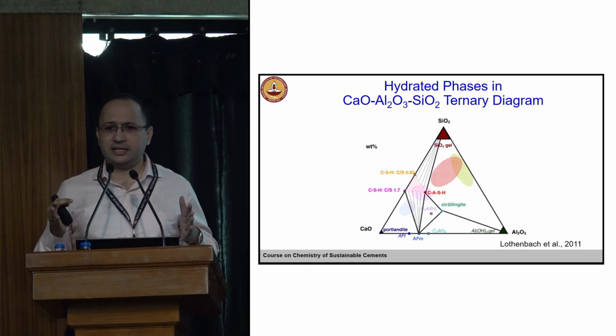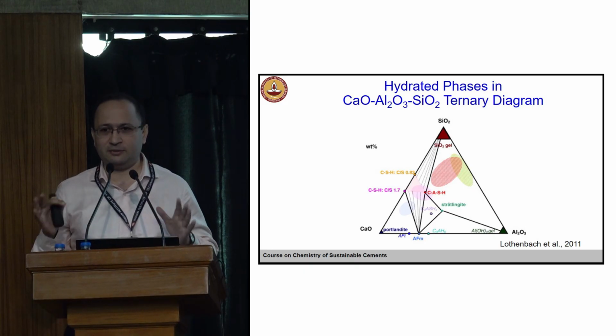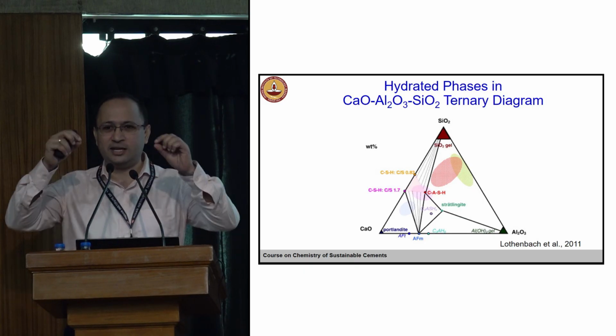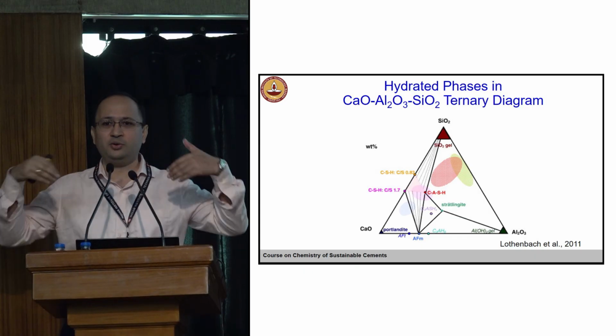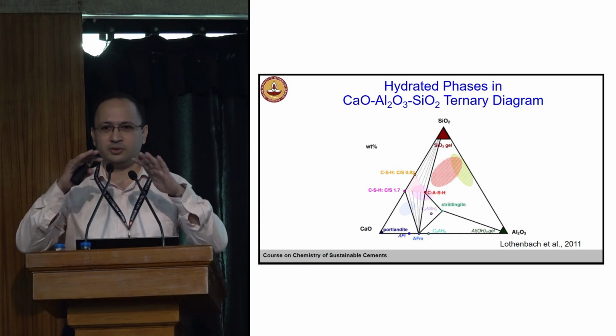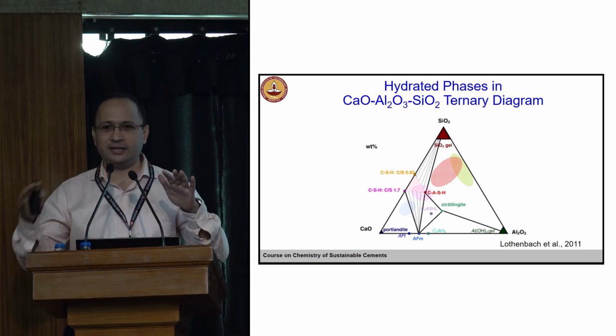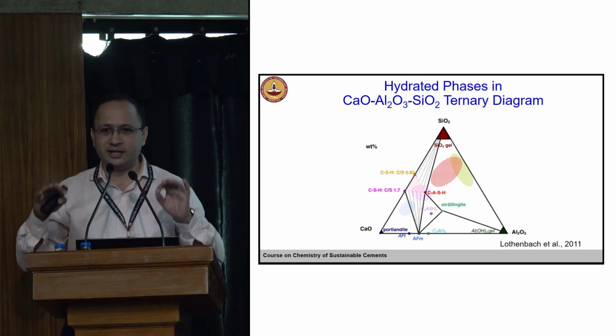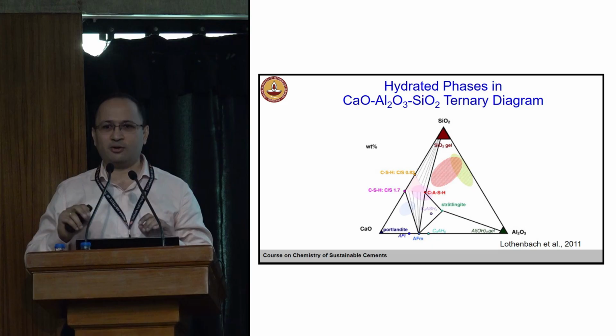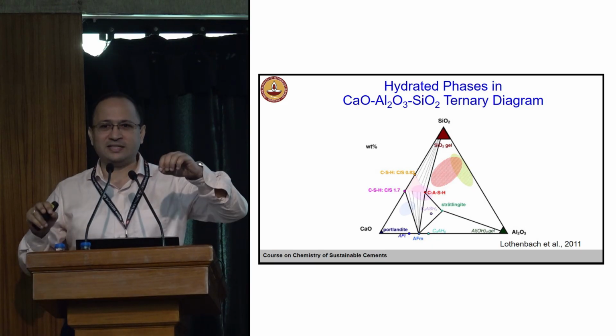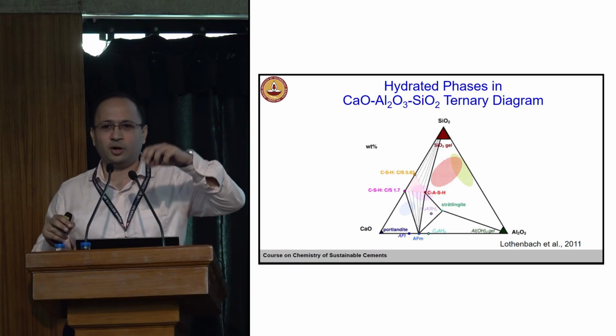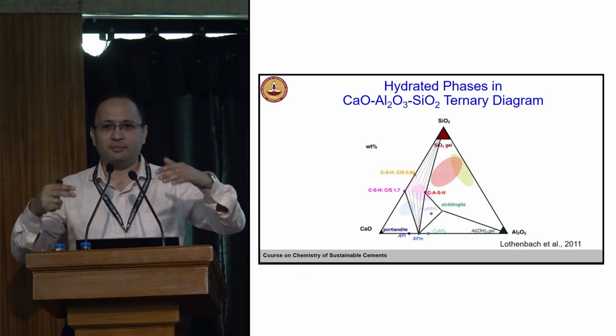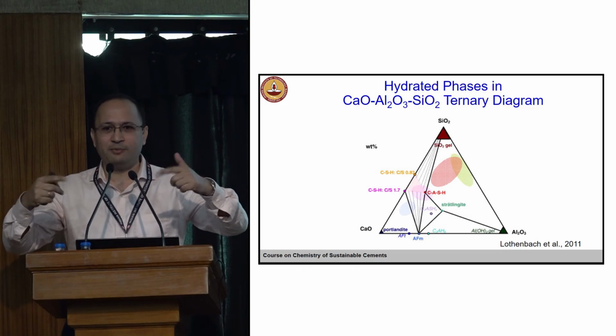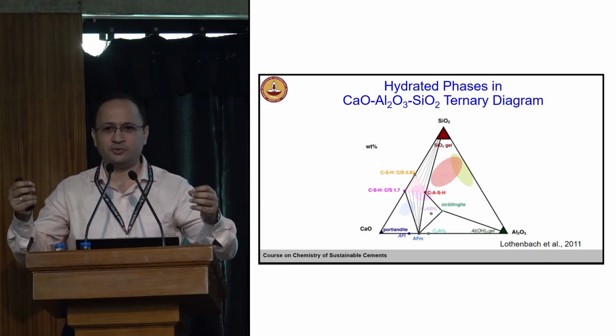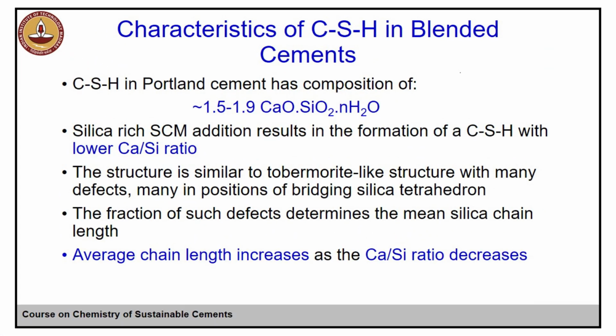Essentially, cement hydration is a dissolution precipitation reaction. If you have to understand cement hydration, things are dissolving, and then new things, reaction products, are precipitating. Dissolution is governed by undersaturation. Precipitation is governed by supersaturation, right? A simple example is, if you start adding salt to water, initially you won't see it, but if you reach that limit, it becomes supersaturated, you see deposition of salts, right?